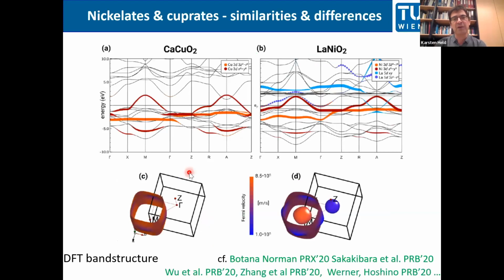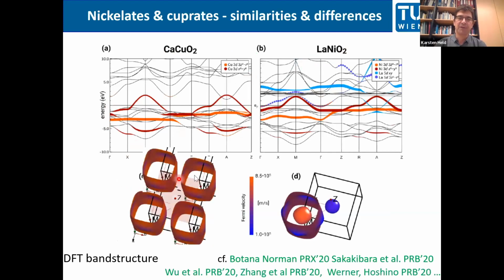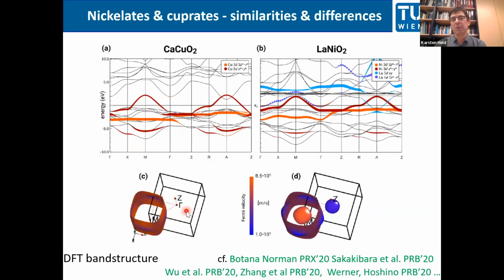But now let's look into the electronic structure, and let's start from density functional theory, comparing a cuprate and a nickelate here. So in DFT, you have this nickel x squared minus y squared orbital crossing the Fermi level. So you have a hole pocket, or in the Brillouin zone in pink, you have 4 of these Fermi surface sheets in the cuprates.